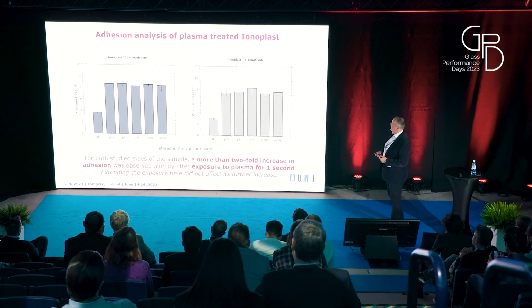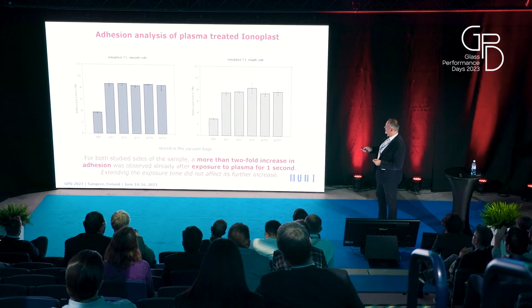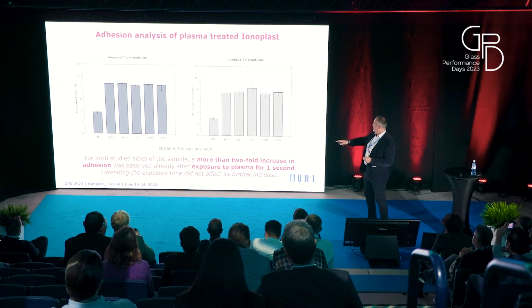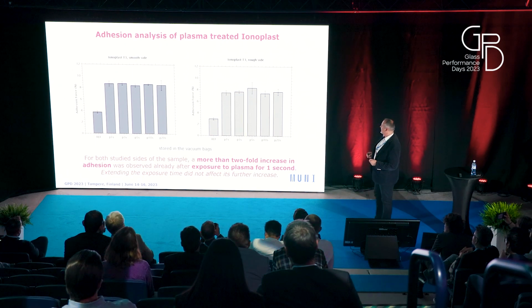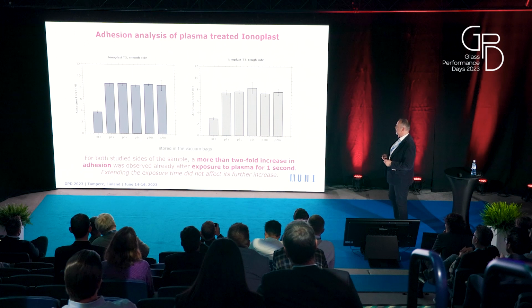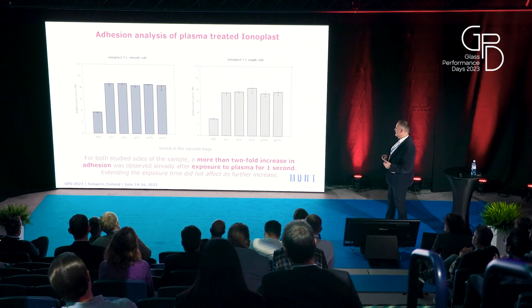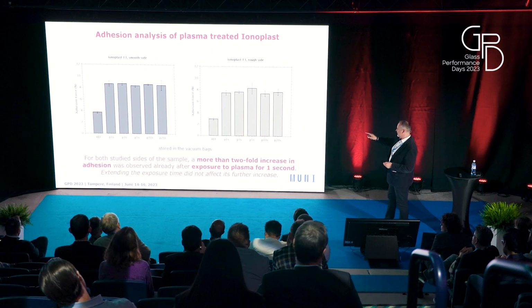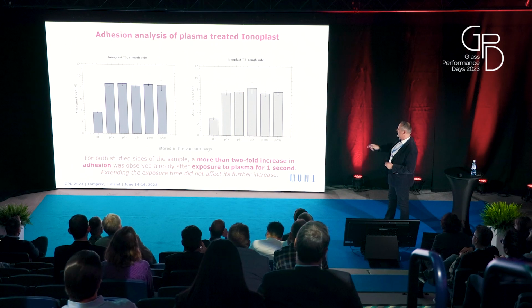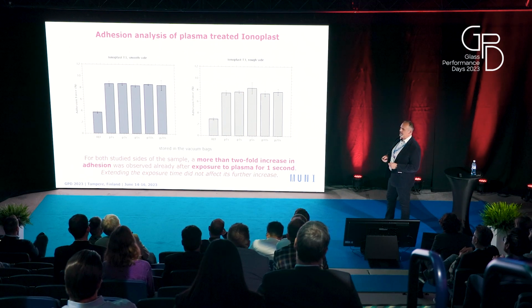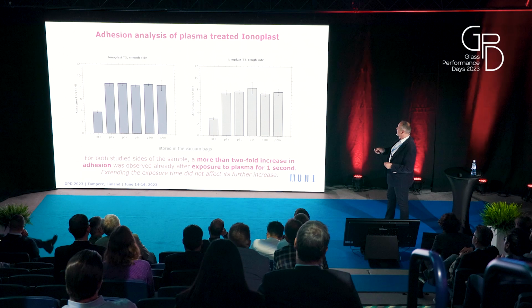And on the graphs, we can see that after 1 second exposure time, we observe more than a 2-fold increase in adhesion. So it is really, really short time. And it is also interesting that extending the exposure time did not affect its further increase.